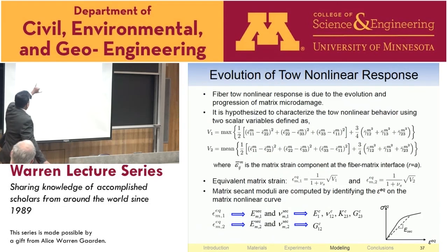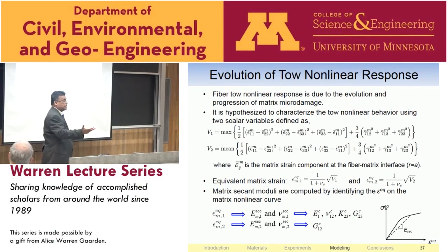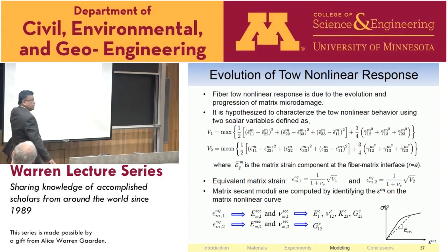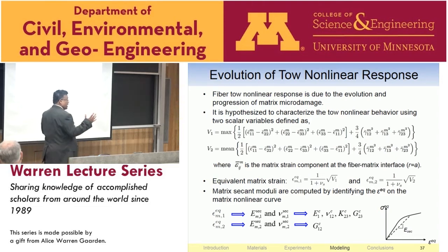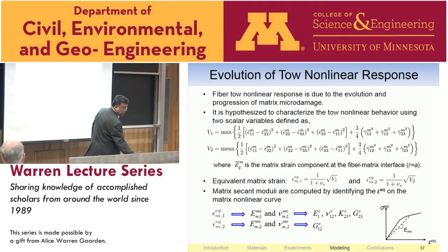How do you evolve the tow nonlinear properties? Again, in the morning, I had a great conversation, very short but great conversation. Triaxiality, right? The tows inside are not under uniaxial stress, they are under triaxial stress states, right? Here in this department, there's a great lab that can do work where you can not only change the triaxiality, but you can control how much in different directions you can load the material. So that's a great resource for getting data of the type that we need for this. So here we have two quantities, V1 and V2. These are basically the von Mises equivalent strain expressions. But what we found was that the mean controls how the equivalent stress and equivalent strain evolves, while the max actually controls the details of the shear evolution. It's a very interesting observation. Why? We are still trying to understand why when we do the experiments, but it turns out that that's what it is.